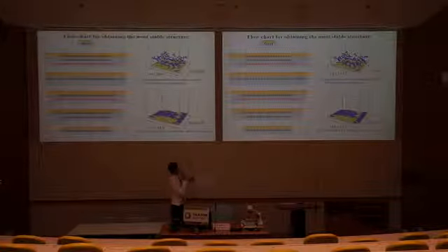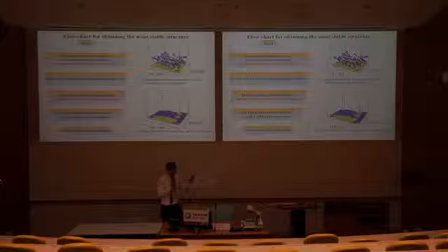This is the flow chart for obtaining the most stable structures at the 4 different coverage ratios. First, we deposit different numbers of STA molecules on the same size graphene. This figure is for 80 STA molecules on this size graphene. We apply external forces to make the STA molecules adsorb on the substrate.